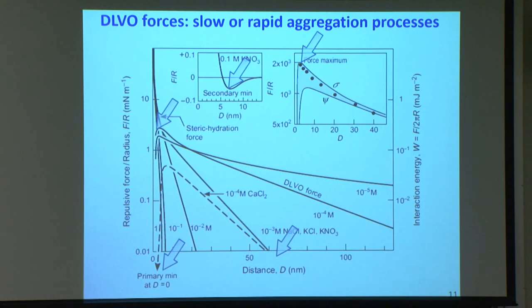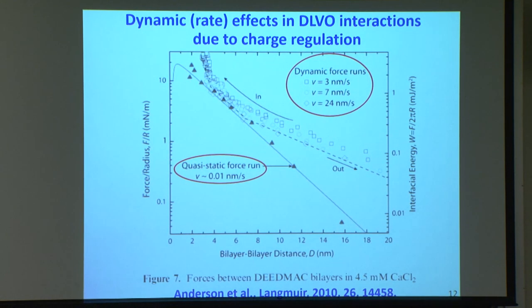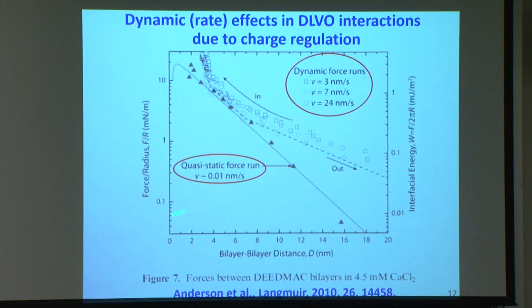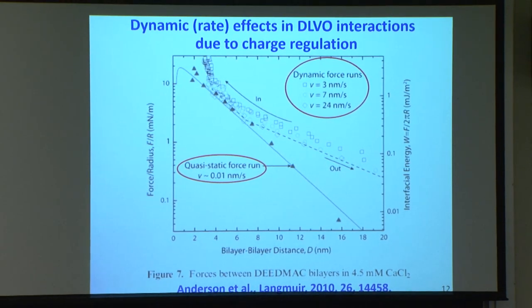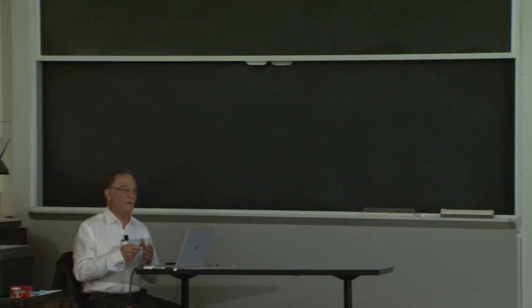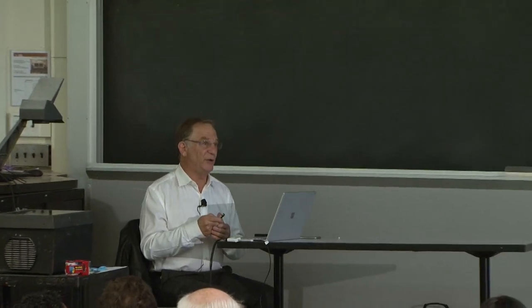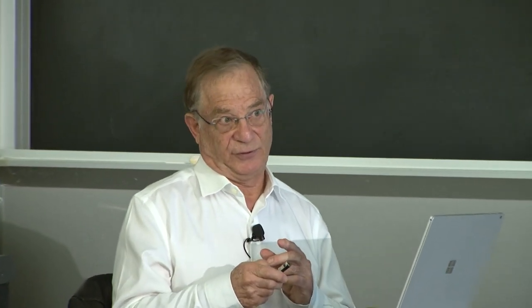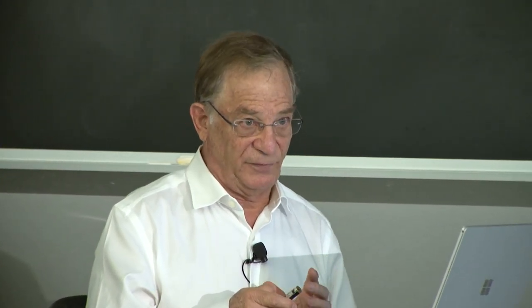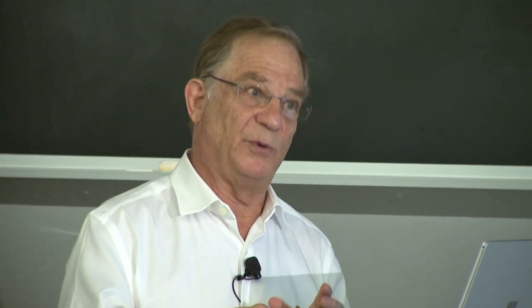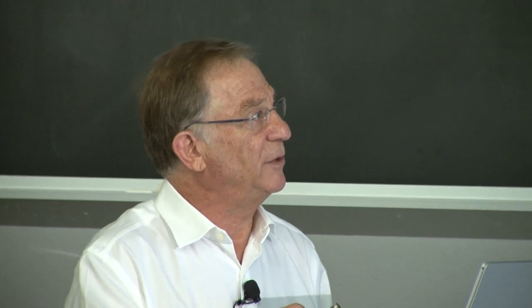So the first experimental results I wanted to show, which illustrate the important effects of time, is what happens when you measure these forces. This is the repulsive force as a function of distance at different rates. Now, when two surfaces approach each other, some ions will adsorb on the surfaces and exchange with ions on the surfaces. This is known as charge regulation. You're forcing ions back on the surface, and it takes time for ion exchange. People usually think that only depends on the diffusion of ions in and out of the gap. No, it also depends on the exchange once the ions are on the surfaces.